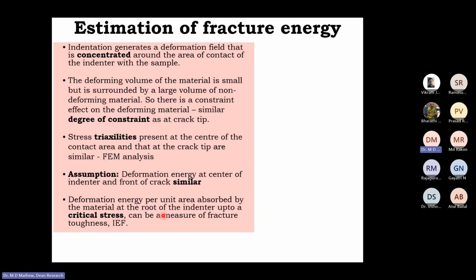Then it is assumed that the deformation energy at the center of the indenter and at the front of a crack are similar. If that is so, then the deformation energy per unit area absorbed by the material at the root of this ball indenter up to a critical stress can be a measure of the fracture toughness of the material. That is what is called indentation energy to fracture, which would mean that if I were to continuously allow the indenter to penetrate the material to a depth that will generate a stress equal to the fracture stress of the material, then the energy absorbed in that process can be correlated with the energy for fracture.